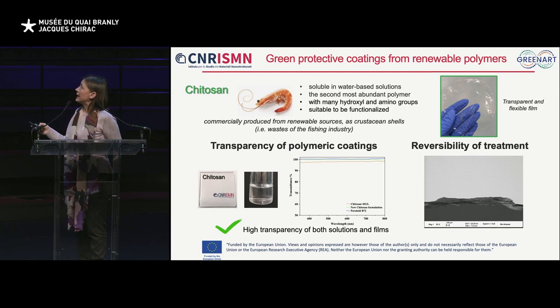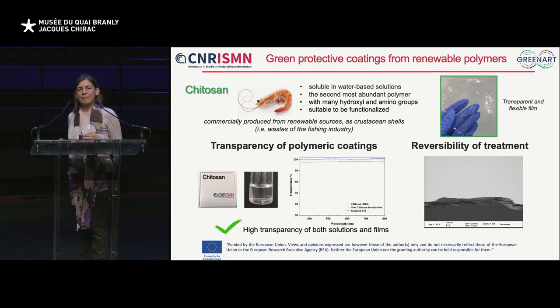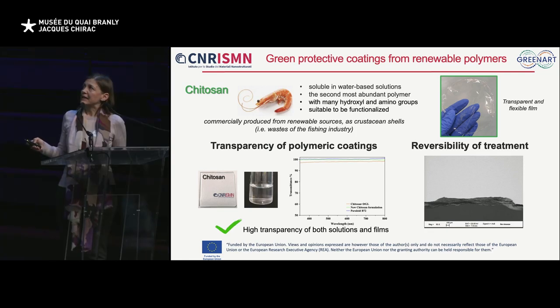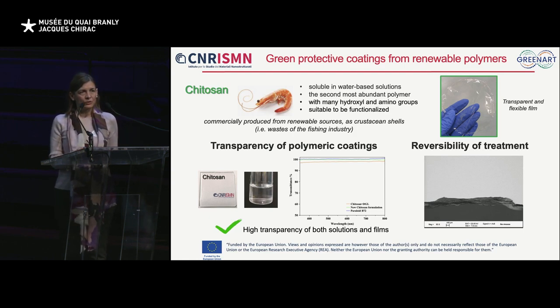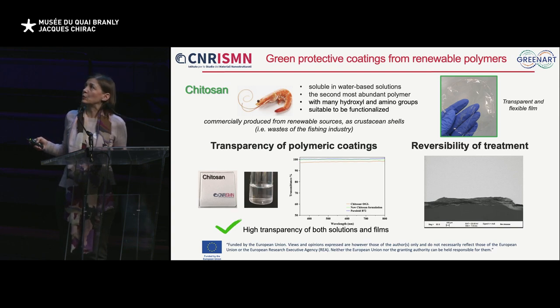For example, you can see a thick film prepared with the biopolymer, and in particular by using the new formulation, and we can appreciate the high transparency of these materials. But in addition, also the transmittance measured by UV-visible spectroscopy shows that we have a very good transparency.